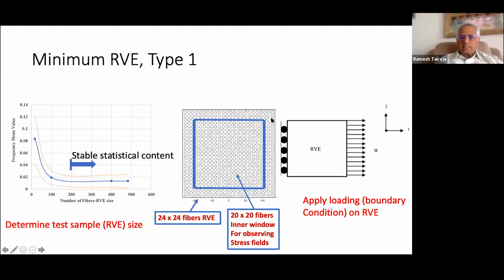You put additional fibers around it to protect that window from edge effects. So you're applying the uniform displacement to this RVE. The edge effects will be in this region. You go away from it and do your failure analysis in this region here.